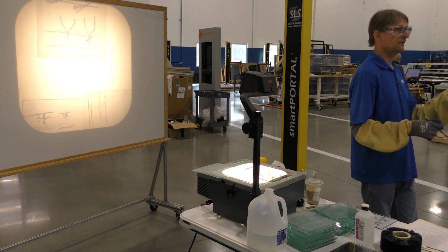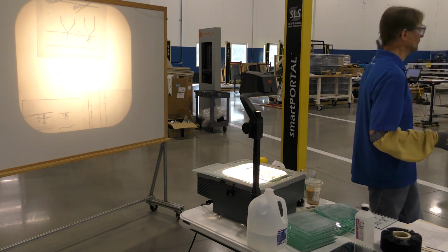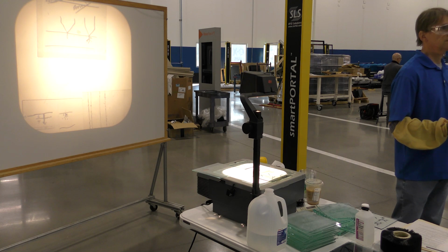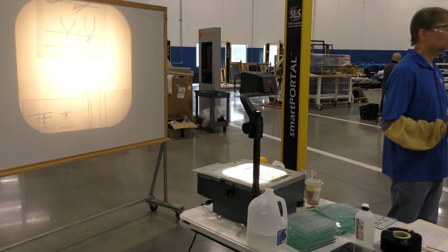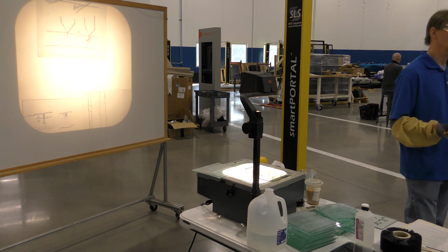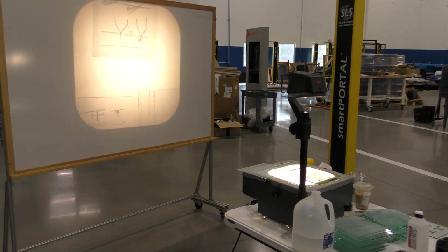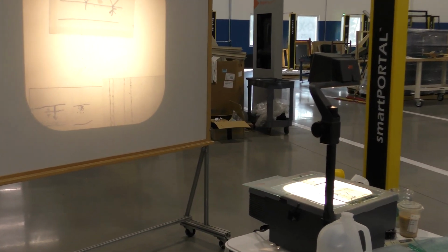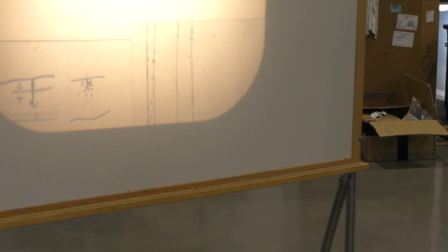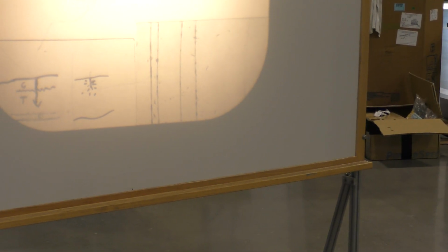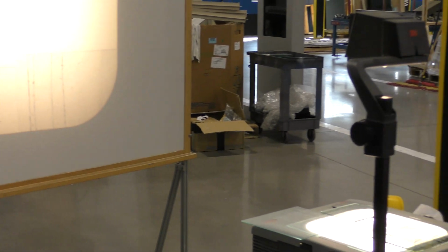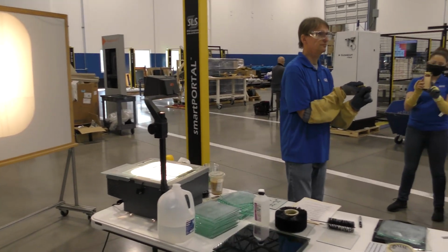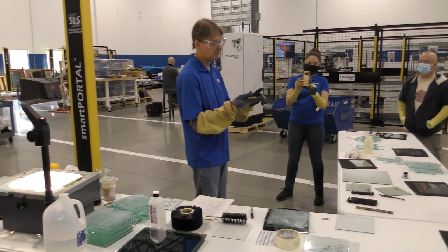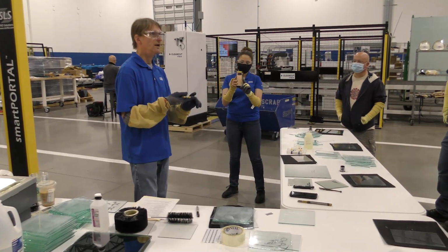Or if your cutting fluid does not have that evaporative rate that is desired for the throughput rates that you have. So there's a whole bunch of different types of cutting fluid that have different rates of evaporation. Some evaporate very quickly, in a matter of seconds. Some take minutes, some take a very long time to evaporate. So you want to make sure that the cutting fluid that you're using is, number one, water soluble. Don't use kerosene, don't use olive oil, don't use any of this stuff.